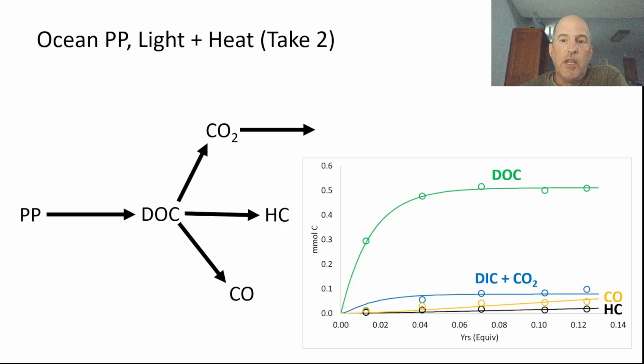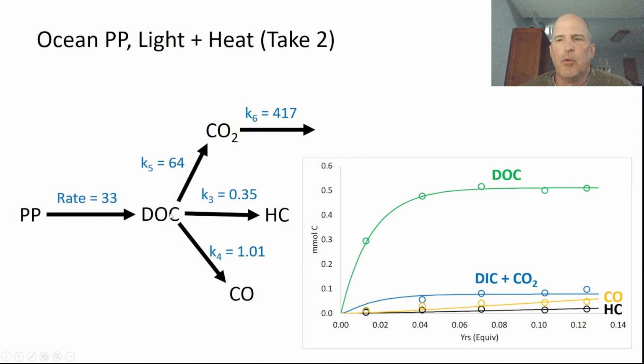I mean, it should be. I mean, it's basically the same fit as before with that rate constant for polypropylene going to CO2 set at 0. I don't think that you can say anything about the hydrocarbons and the CO, where they come from based on this, but it seemed more intuitive to me that if the CO2 is coming from the dissolved organic carbon, these other products probably are as well. And so this is the model I stuck with. The rates here now, that rate of polypropylene going to dissolved organic carbon, that's the degradation rate.